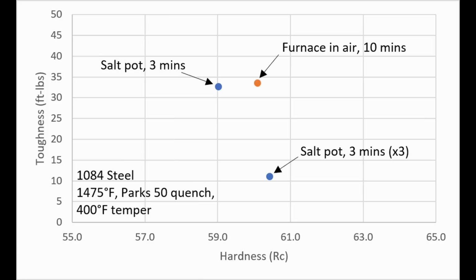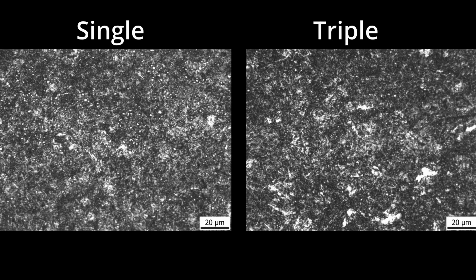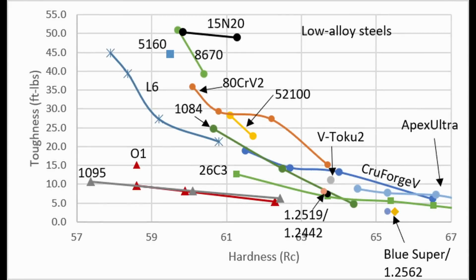Somewhat surprising was that the salt pot heat treatment triple quench did much, much worse for toughness. The hardness was a little bit higher, but the toughness much lower. And this was pretty surprising. So I looked at the micrographs of the steel, and as expected, the triple quench that went in 3 times at 1475 had much less carbide. So I think what happened is that we ended up with excess carbon in solution. That can lead to plate martensite and other factors that lead to reduced toughness, because the toughness with the triple quench was much closer to a high carbon steel like 1095 or O1. Those steels in the past I have seen relatively low toughness values because of their extra carbon in solution.